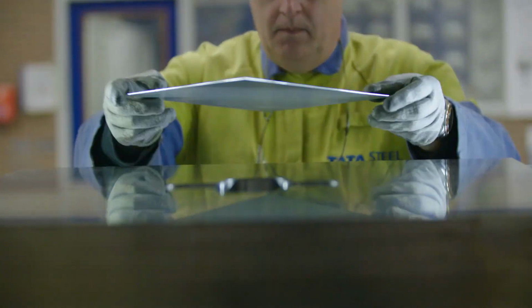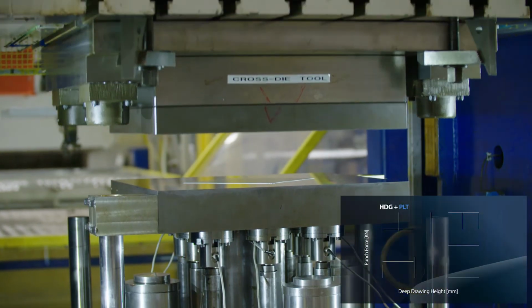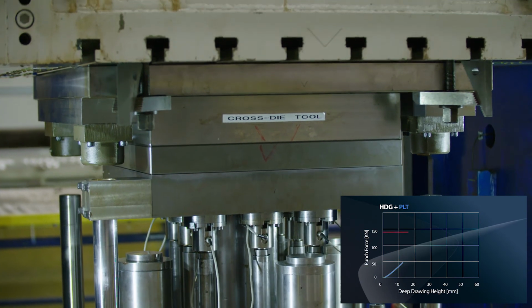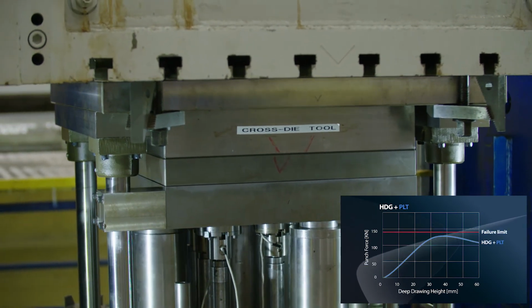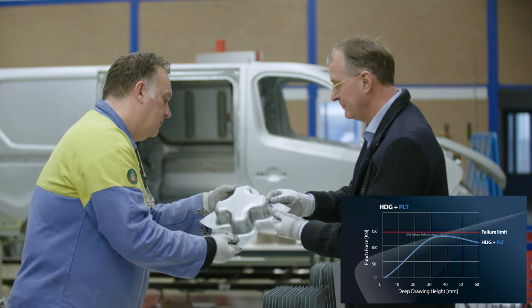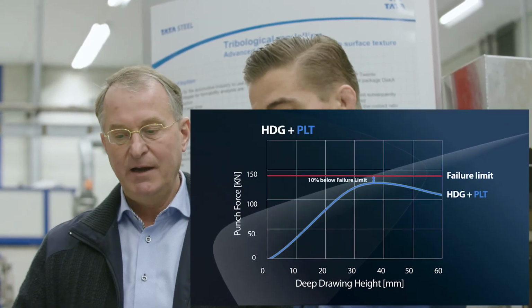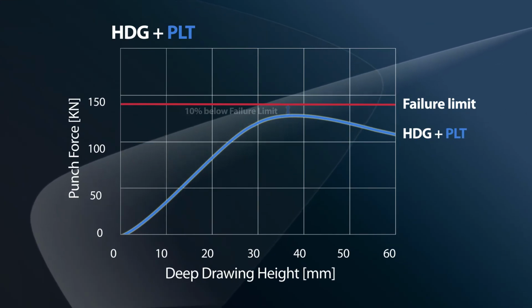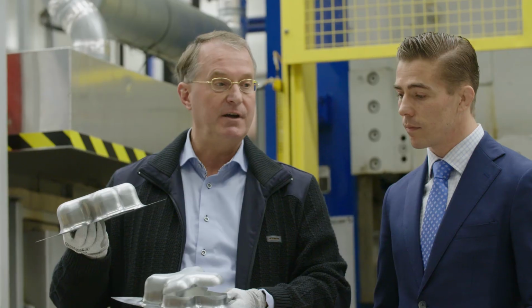We observe that PLT has a smooth sliding without any noise in friction and sound. With PLT, we measured much lower punch force in critical deep drawing situations, up to 10%. From our series of tests, we can conclude that PLT offers much better friction behavior. And because PLT offers better deep drawability and a lower level of tool pollution, it is really the key enabler